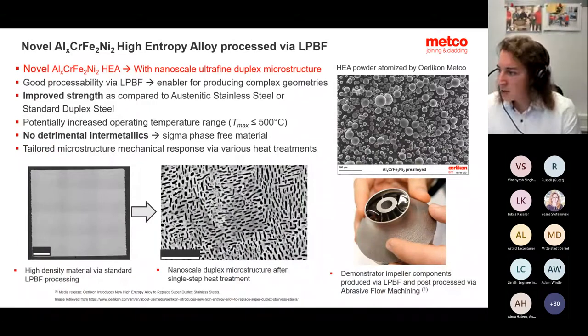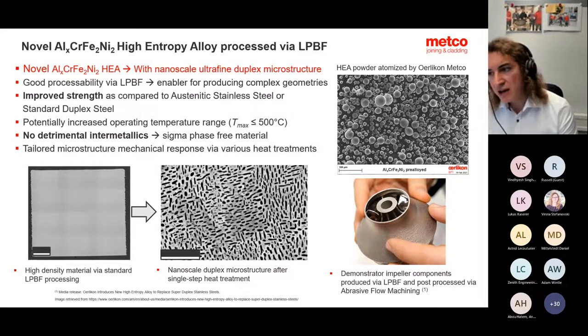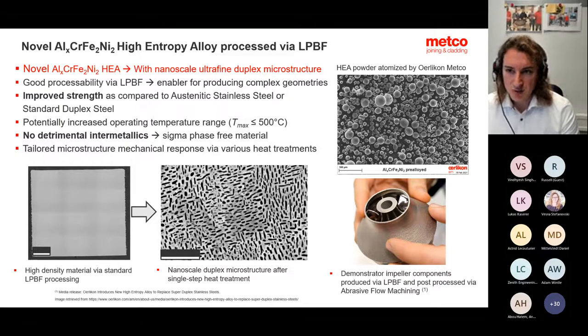Last but not least, what I would like to introduce to you is also a new high entropy alloy, which we have developed primarily for powder bed fusion, but the material properties were from the beginning introduced in a way that it can also still be used for DED. And for example, where you need improved strength compared to austenitic stainless steel or standard duplex steels, which are very hard to deposit, this type of high entropy alloy was developed.